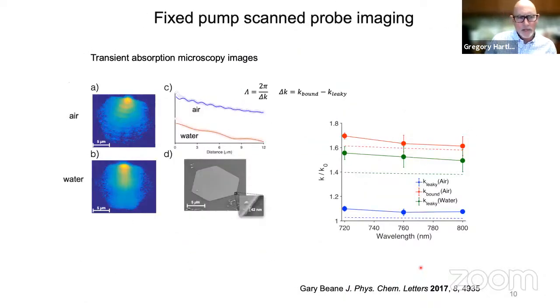This is an example of that other sort of imaging where you focus the pump laser at a spot in the sample, and then you scan the probe to make an image. And this is, again, of the plasmon modes of a single nanoplate. Our pump is focused at this point in the plate. We scan the probe around the structure and we get an image. The most striking thing about this image is that you can see these waves emanating out from where we excited the sample.